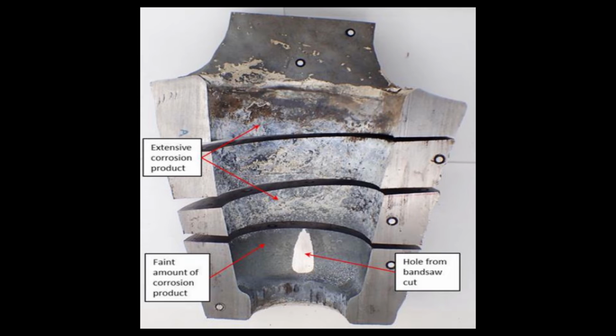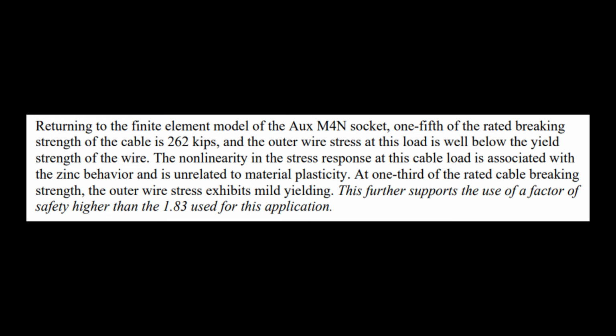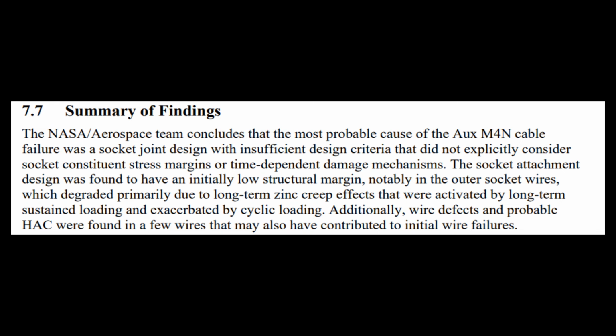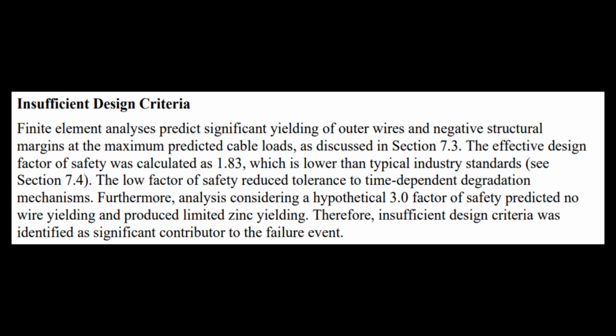The NASA report examines many causes of failure, among them corrosion, faulty design requirements such as factors of safety, and long-term stresses causing creep failure. The NASA report states that design criteria had a 1.83 factor of safety on rated breaking strength without consideration for constituent stress margins. Loads predictions reviewed after the failure indicate up to 15% higher than design criteria and a less than 2.0 factor of safety.